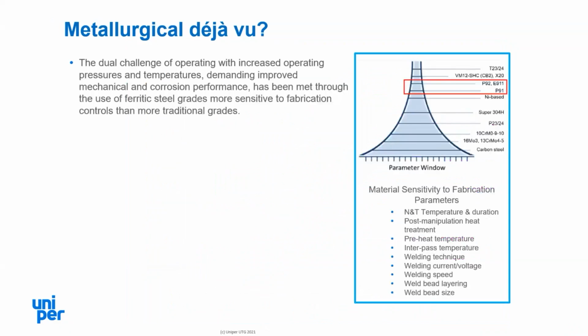However, for ferritic steels, the dual challenge of meeting the more onerous operating conditions, particularly pressure and temperature, as well as quite often corrosion performance, has largely been met through these ferritic steels with increasingly exotic additions to them. And as they become more exotic, so they become more sensitive to the quality control implemented during the fabrication stages, both in the workshop and on site.